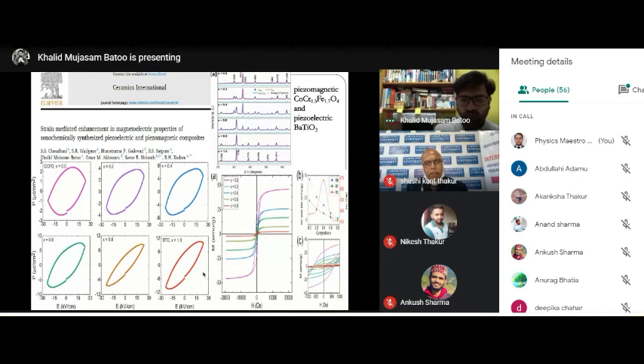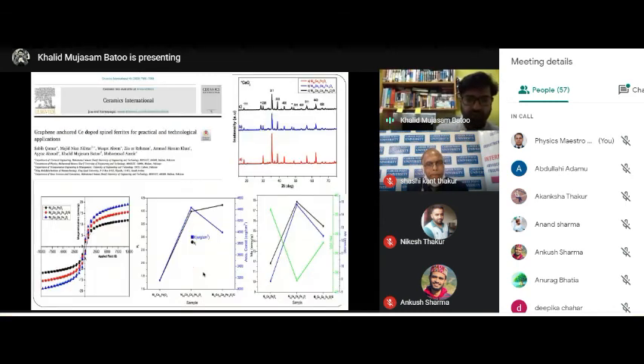That was one important aspect we found, how to tune the properties of these materials. So it suggests that if you have the right kind of doping, the right kind of matrix, and the right kind of composition, you can tune the properties of these materials and miniaturize them as per the design of your experiment. This is another aspect of the magnetic materials I'm going to talk about.